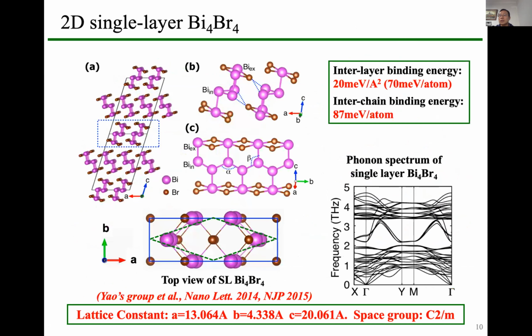So our calculations show that the interlayer binding energy of bismuth bromide is only about 20 meV, and the interchain binding energy is about 87 meV per atom. So these numbers are very close to each other and very close to the interlayer binding energy in graphite and molybdenum disulfide. So this material can be very easily cleaved to form flat surfaces and form nanowires, because they are essentially coupled by Van der Waals interaction.